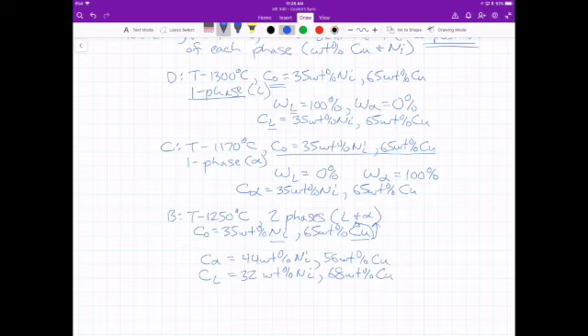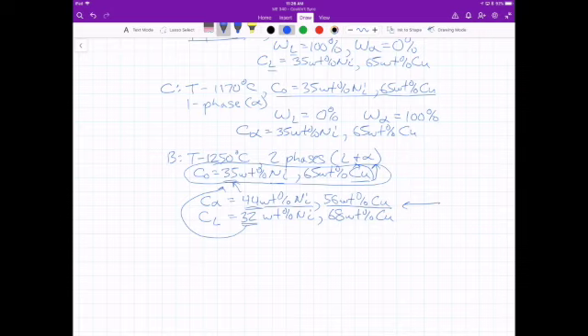So what does this mean? The initial concentration, like I said, is always the same. What we're seeing is there's a tendency for more nickel to be solid than its initial concentration, and less nickel to be liquid than this initial concentration. So this is just a fractional average. The weight fraction gives us the amount of each, and if we multiply the weight fraction by the concentration and add them together, we will get this number. So we have our composition or concentration of each. It's always in weight fraction, and it has the element, the component that is added, as part of the units. So there's our answer for that one.